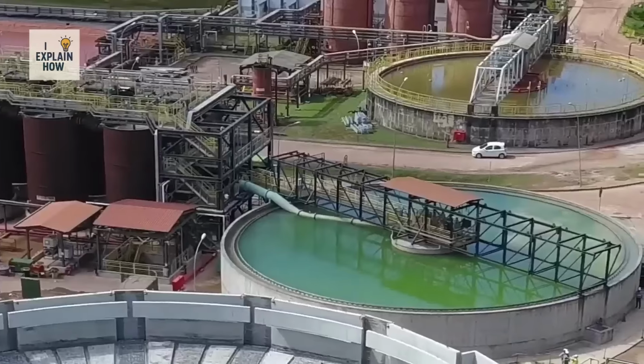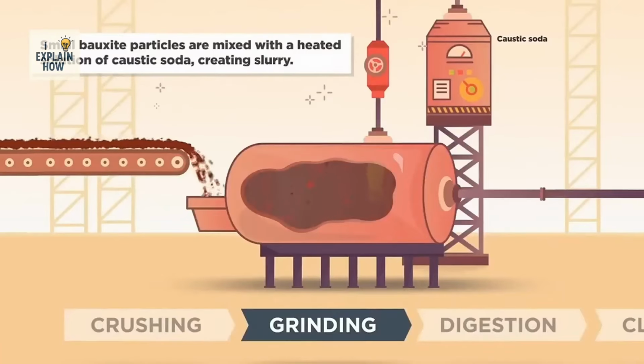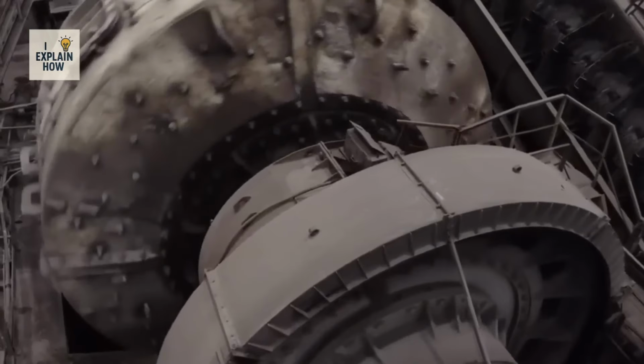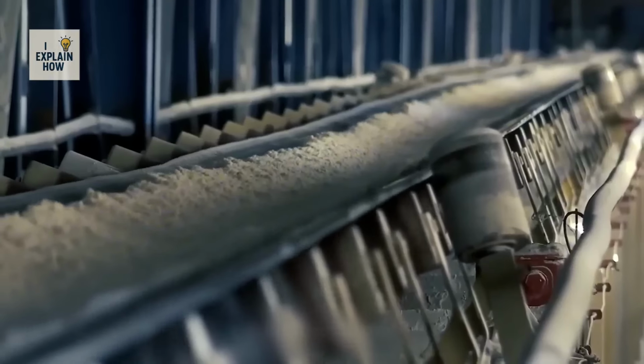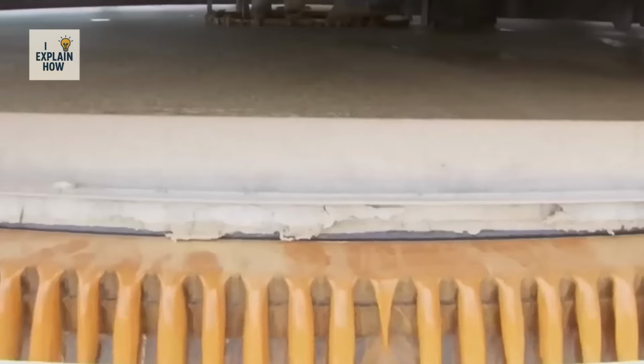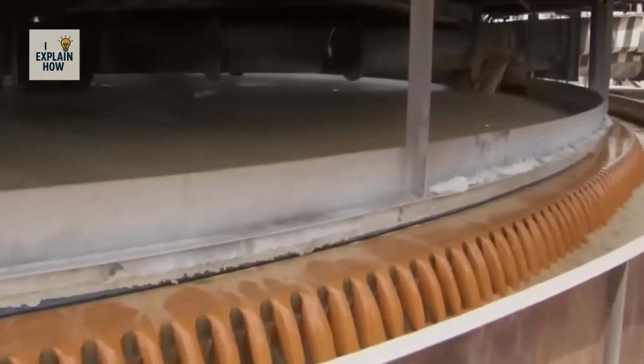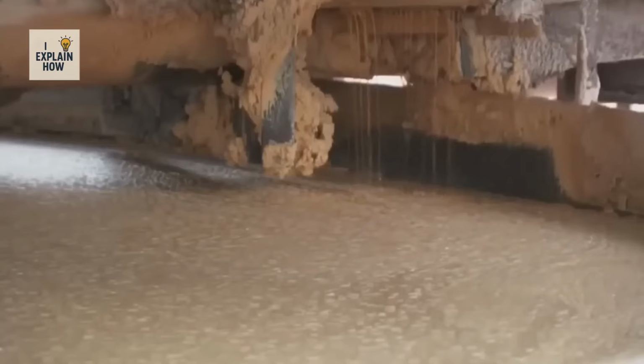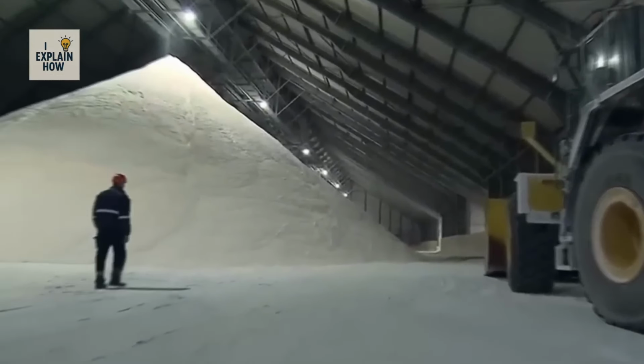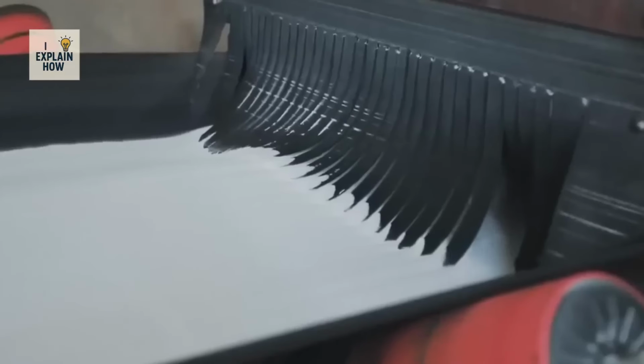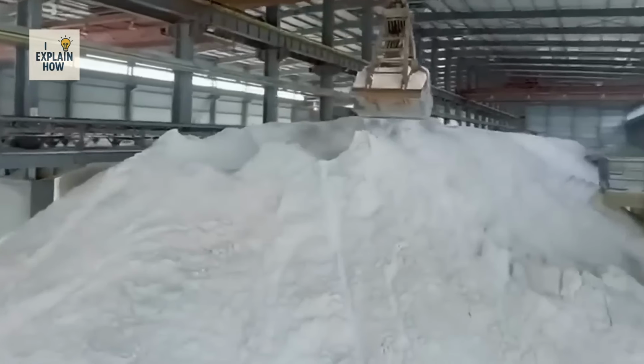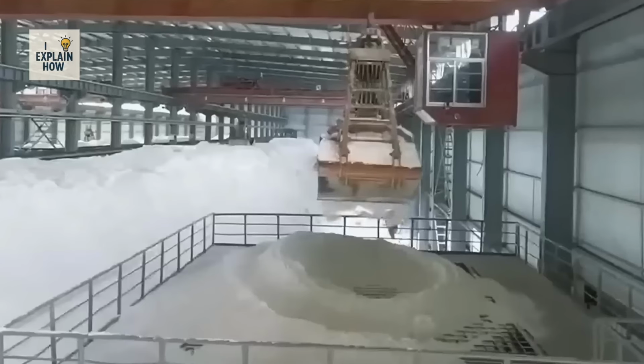To extract aluminum from the ore, a refining process called the Bayer process is used. A conveyor belt deposits the ore into a giant rotating drum where enormous steel balls grind it into a fine powder. The bauxite powder is then mixed with a caustic fluid that separates the aluminum oxide from the rest, producing a concentrated aluminum oxide solution. And then comes the most surprising part. This solution dries and forms sandy crystals called alumina, the substance from which aluminum is made. The next step is to isolate the aluminum from the oxygen.